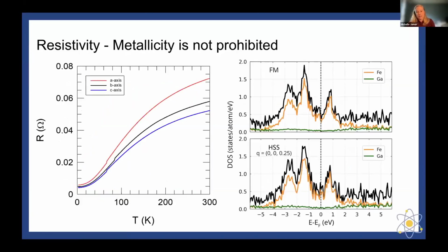Whenever we're talking about the resistivity of the compound, it's interesting because we do have an antiferromagnetic-like state, and what we have is that metallicity is not prohibited. So it's interesting to look at these antiferromagnetic metals because they're being proposed for various applications. And what we see here, using DFT in either the ferromagnetic or the helical spin spiral state, is that we still will have something that looks somewhat metallic. And when we take a look at the resistivity versus temperature graphs, we see that we do have the increase of the resistivity with temperature that's indicative of a metallic-like material.